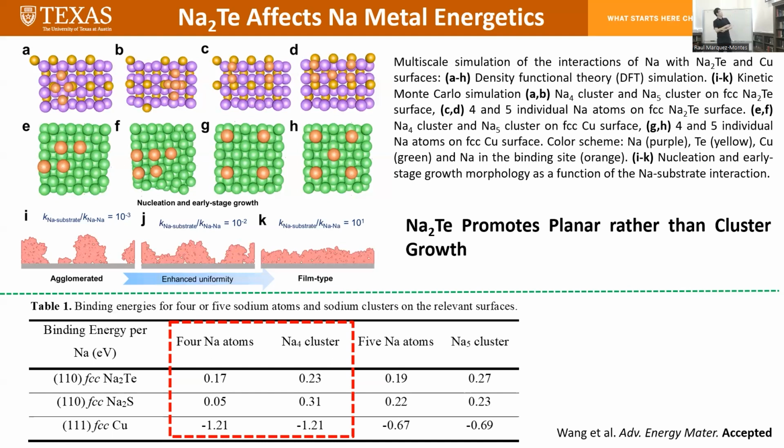However, for the tellurium and sulfur modified ones, the atomic binding energy is lower compared with the cluster, which proves that atomic growth is more favorable.